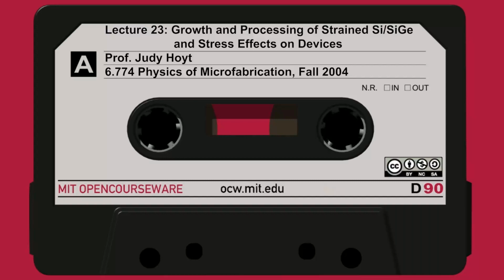So I mentioned to you that arsenic moves faster in silicon germanium. This is actually a big problem if you're trying to make a strained silicon N MOSFET with silicon germanium in the substrate. Let's say you're trying to make shallow source drains. So you implant 50 keV at 3 times 10 to the 15th, maybe a typical source drain implant, and you anneal it at 1,000 degrees for various times. And the dashed lines here are for a silicon substrate, and the solid are for silicon germanium. So if you just look at, say, this red dashed line, for the silicon substrate with this 20-second anneal at 1,000, you have a junction depth about 500 angstrom.